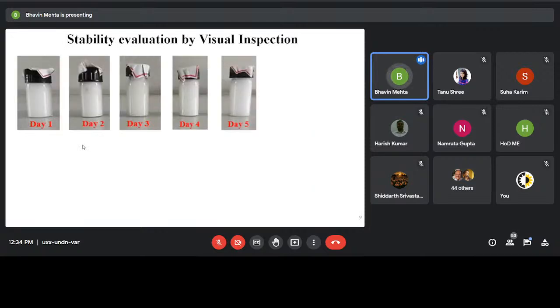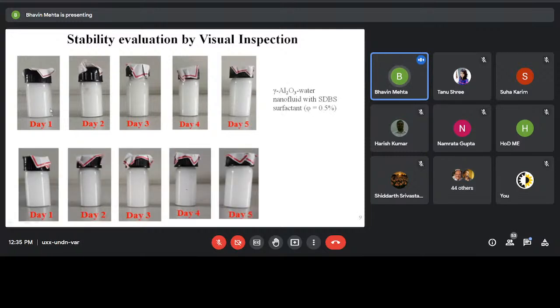Then the stability of this nanofluid is evaluated by various methods. One of the methods is visual inspection, where the sample is continuously monitored for 5 days, and we found negligible sedimentation of the particles, and the fluid could be considered a stable fluid with and without surfactant. The first figure shows the fluid synthesized with the SDBS surfactant, and the second set of photos shows the fluid without surfactant, and both show better stability. Basically, this image is for the 0.5% volume fraction.